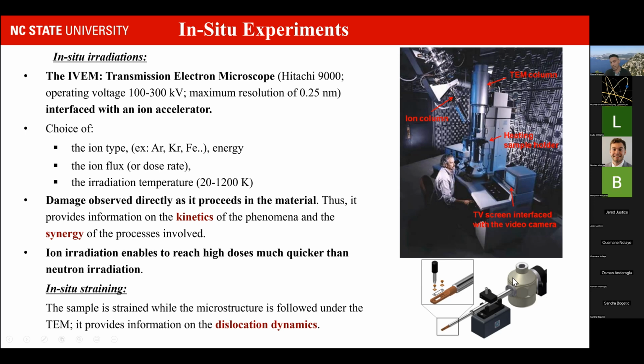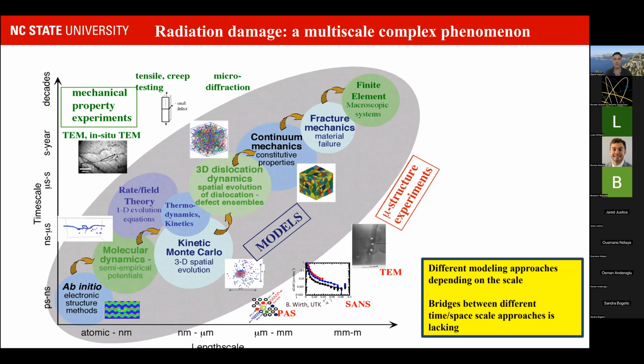A few words about this stage that I put at the bottom. The same type of experiments can be done with a stage that allows you to strain the sample, and there you can look at the dislocation dynamics in the metal. You can irradiate the sample and look at how the clusters and loops forming under irradiation interact with the dislocation dynamics. There are very interesting experiments that can be done to study the plasticity of irradiated materials. For the sake of time, I will not present any of that in this presentation, but I do have some good experiments on nickel-based alloys.